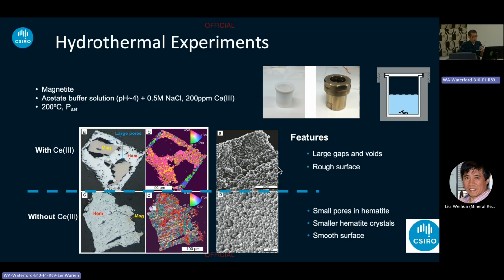Briefly speaking, we have one example here and did the experiment. We took magnetite in the lab, with a fluid simulating what's expected in nature, and dosed the solution with a little bit of cerium and put it in the oven for weeks. After the experiment we see two different textures. When you have a little bit of cerium in the fluid, you see this type of texture, where a core of magnetite is ringed by hematite, replaced by hematite.